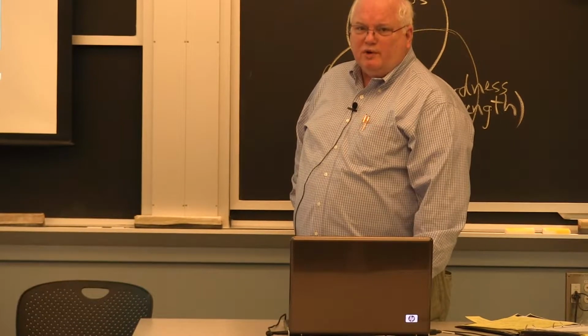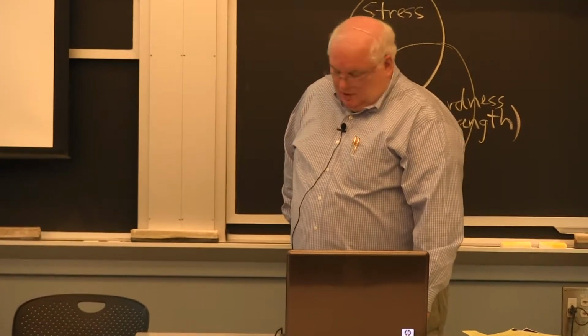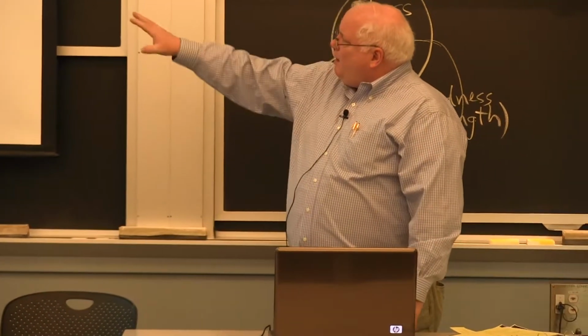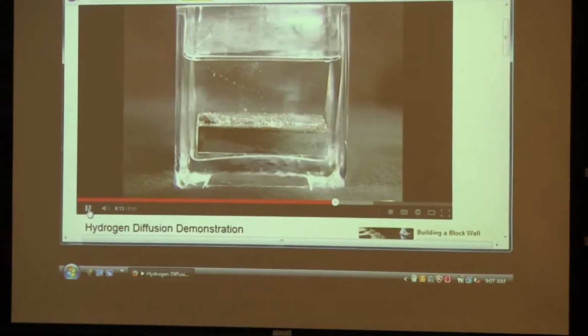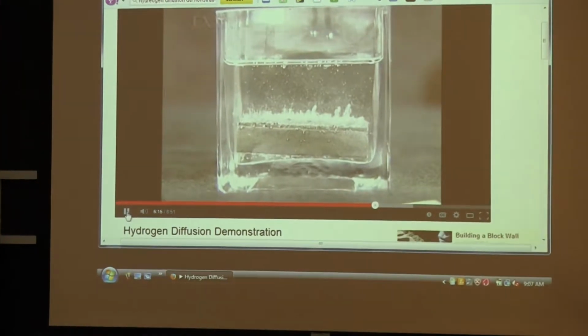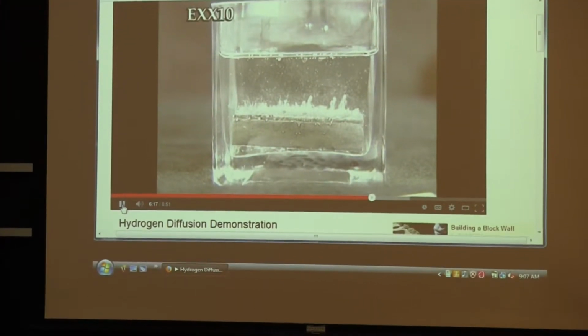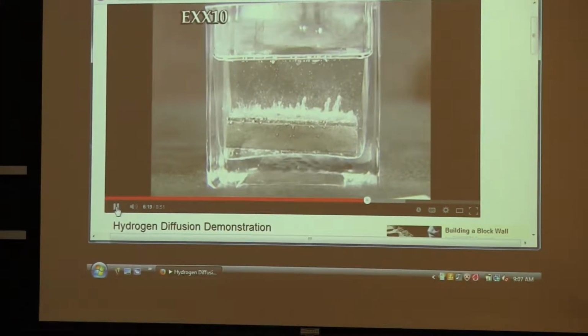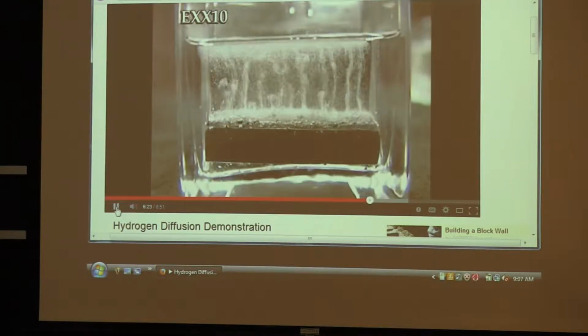None of it really matters too much to just show this. But the guy made a weld. That's glycerin that he just dropped the weld in. And you come back a few minutes later and you can see the hydrogen bubbling out of the weld. So this is sort of like my Sprite, where you saw the bubbles, except this is in glycerin, so it retains the bubbles. They don't pop to the surface within a fraction of a second.